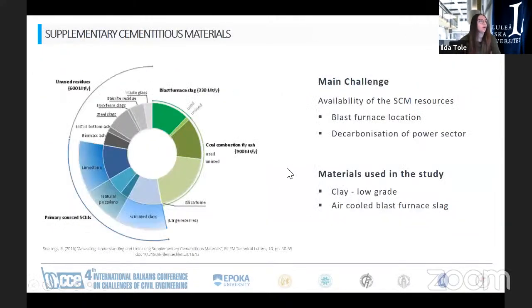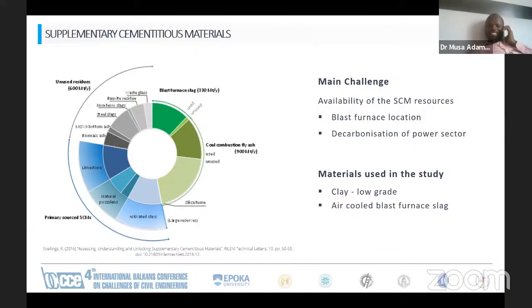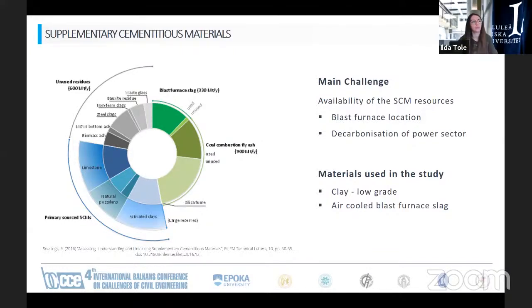In this study, we are utilizing two different sources: mainly clay as a low-grade supplementary cementitious material, and air-cooled blast furnace slag. If we look at the overall presence of these supplementary cementitious materials, we can see that there are different sources, and some of them have a main challenge in being available as resources. For example, the location of blast furnace slags, or the decarbonization of the power structure, which is reducing the amounts of fly ash materials.